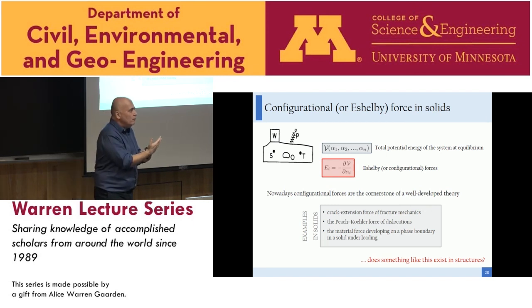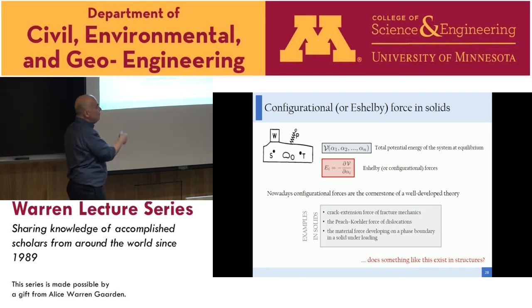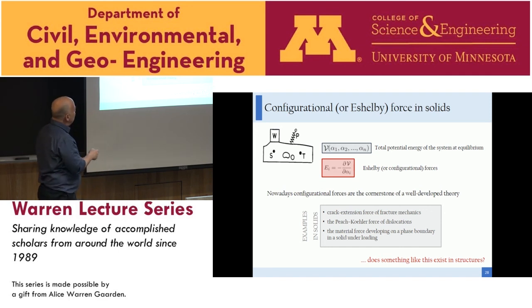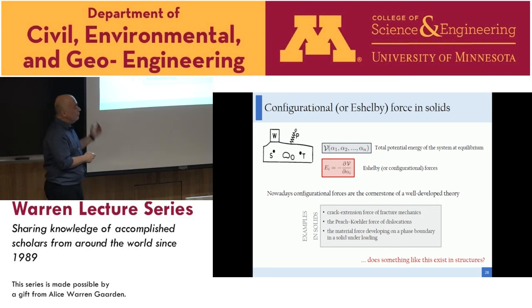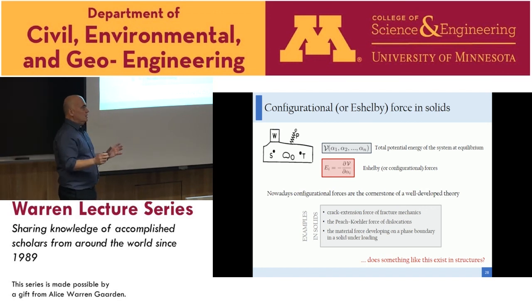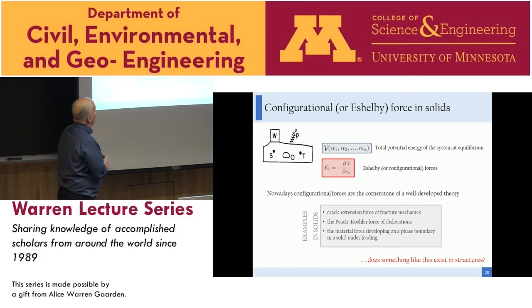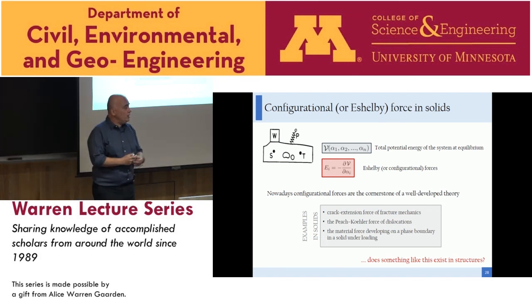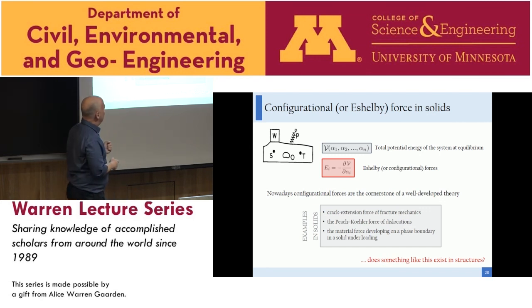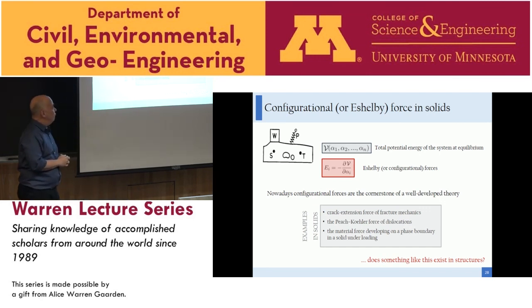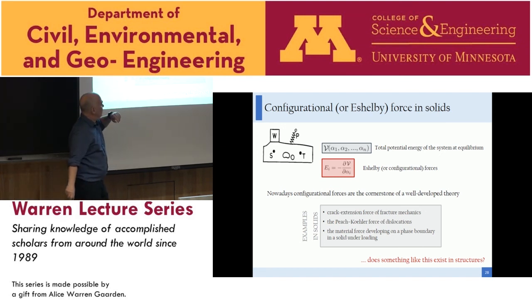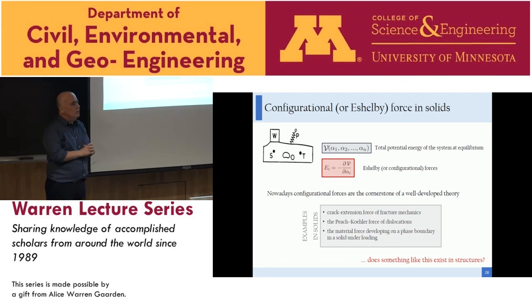Taking the gradient of the total potential energy with respect to the configurational parameters with reversed sign gives a force — the Eshelby force — which is believed to drive defects inside the body. Examples include the Peach-Koehler interaction between dislocations, the crack extension force in fracture mechanics, and the material force developing on a phase boundary in a solid under loading. This concept was extremely successful.